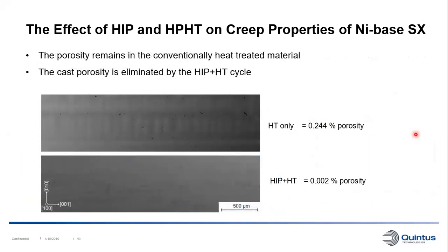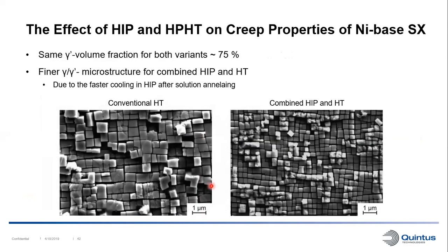And here we can see the results in terms of porosity. As expected for the heat treatment only variant, we still have the casting porosity in there. It's around 0.25%. And in the HIP and heat treatment variant, we can't see any porosity here, which is also expected with the HIP process.